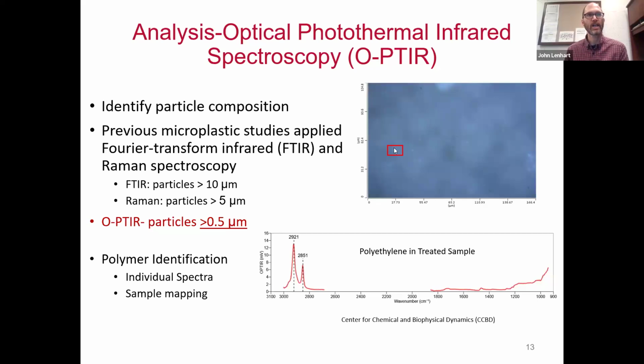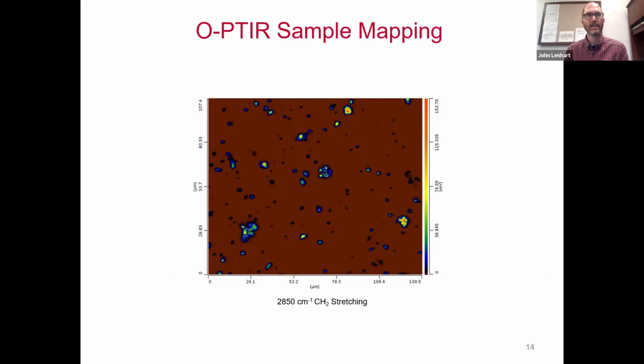For example, it's hard to see optically, but in here there's a small particle that we've identified to be polyethylene. The other way we can use this technique is in a scanning mode. We can identify a particular wave number that's associated with a vibrational feature of plastics. Here we have CH2 stretching, and the image shows particles that are very strong in terms of that feature, as evidenced by the yellow or red, indicating an intense feature. So this we can use to identify the plastics, and then we can collect a spectrum on it. And we can also get sizing from this as well.